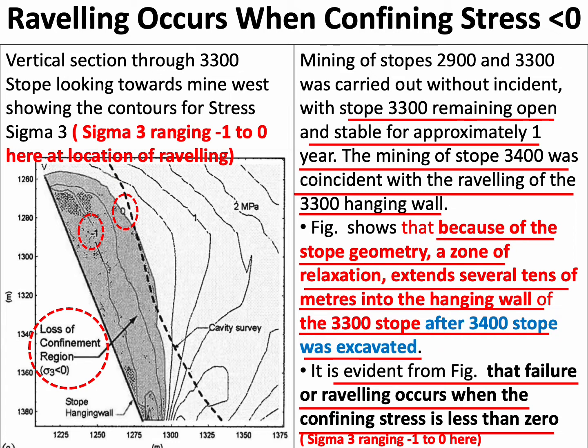But because of the geometry of this hanging wall of stope 3300, with stope 3400 getting started its excavation, the stresses in this zone became tensile. It is evident from the figure that failure or raveling occurs when the confining stress is less than 0. Sigma 3 is ranging between -1 and 0 in this region, and the cavity was formed exactly in the shape of the zone in which the negative stresses have occurred.